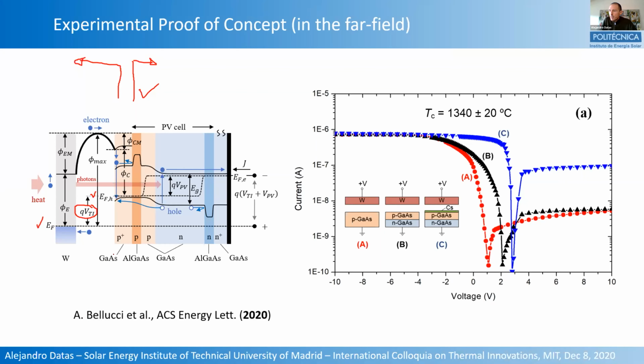In this case, this is a P+ gallium arsenide layer. And then in the photovoltaic side, you have this other voltage, which is the difference in the quasi-Fermi levels of the photovoltaic cell. So at the output, you have this higher voltage, which is the addition of these other 2 voltages. And that basically represents what we have seen here. This is the increment that we see from the thermionic stage alone to the thermionic plus photovoltaic cell combination.